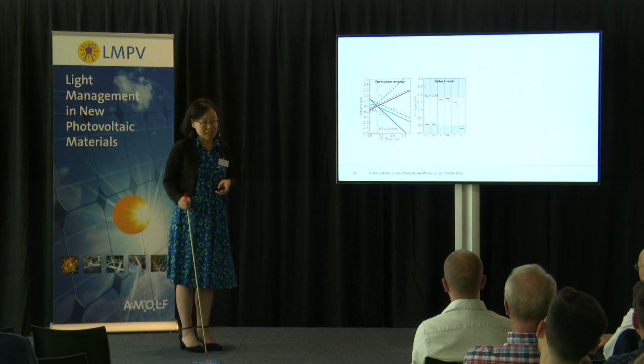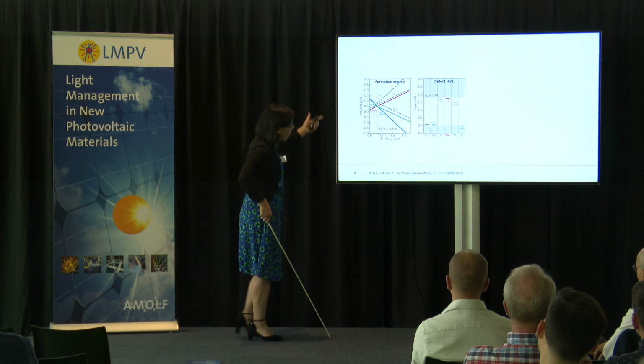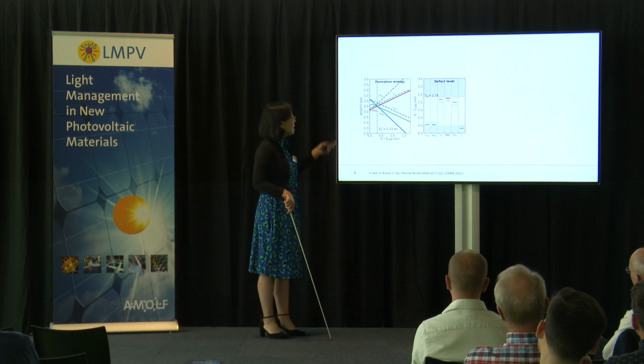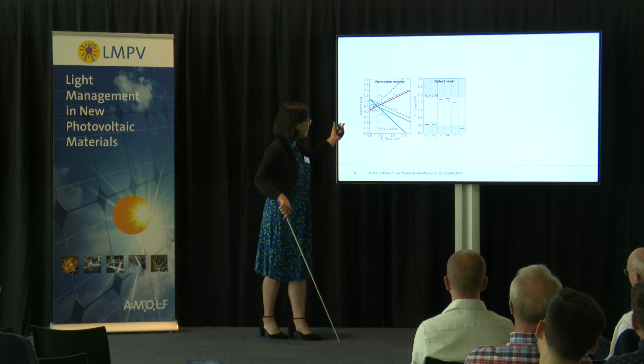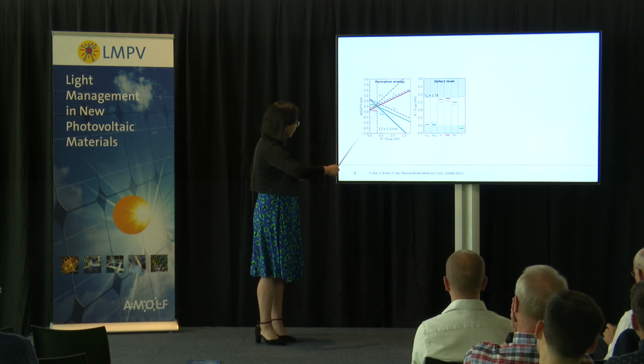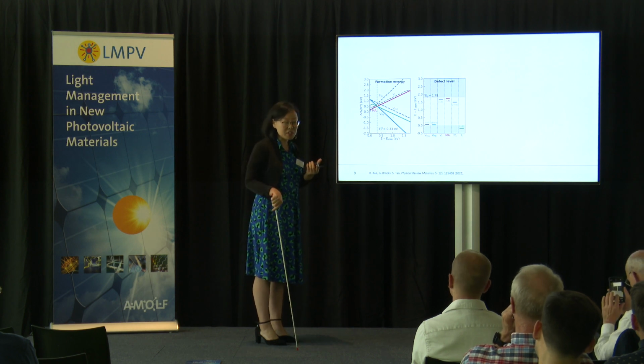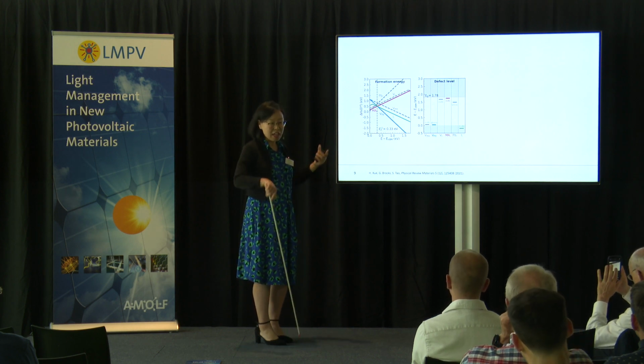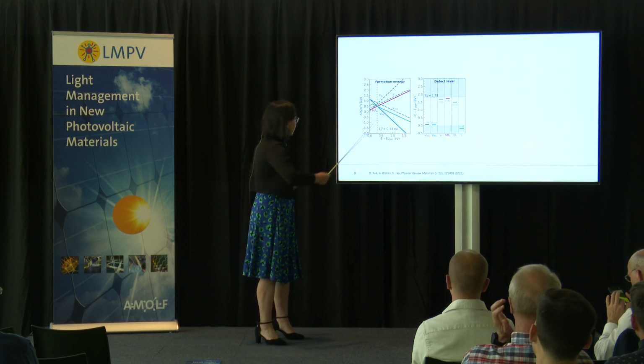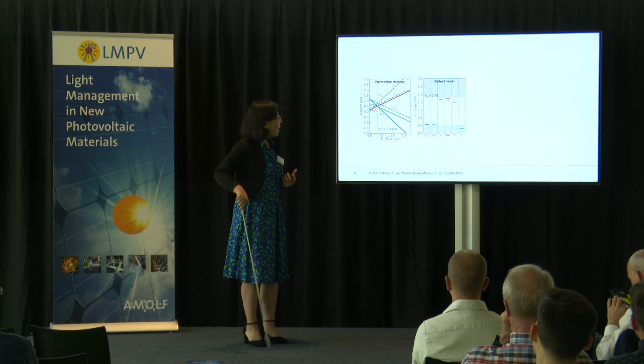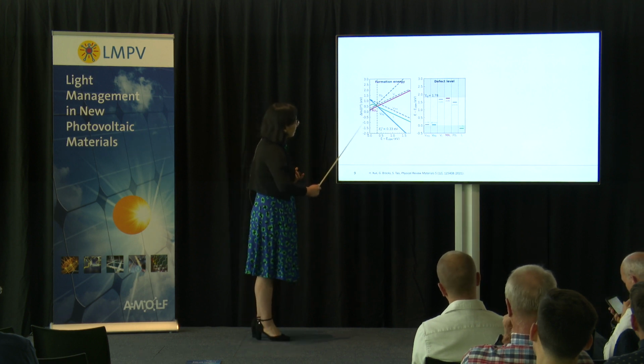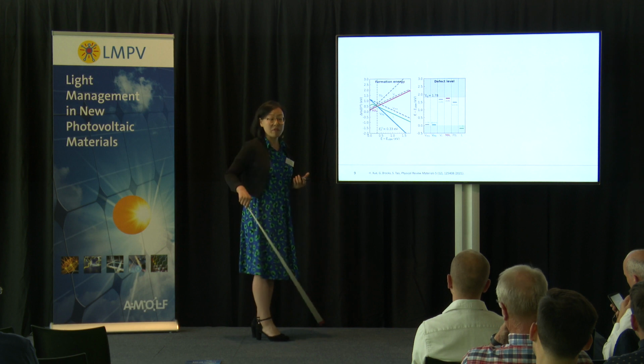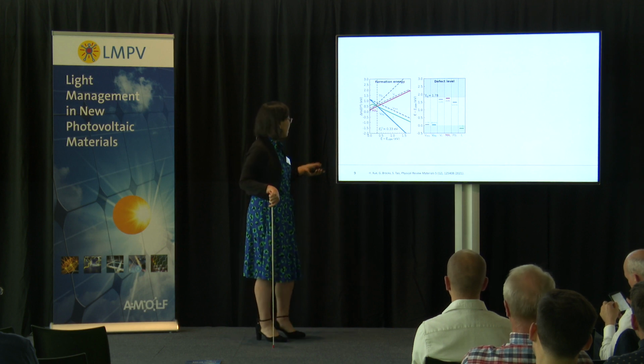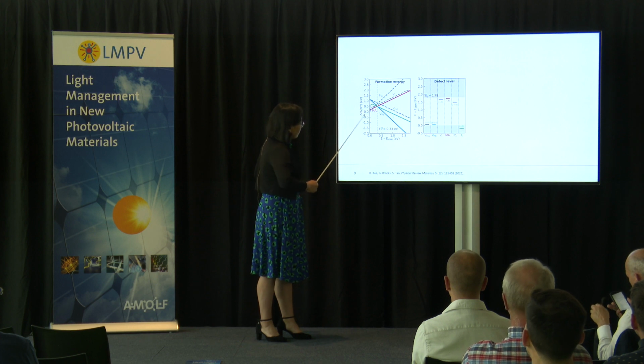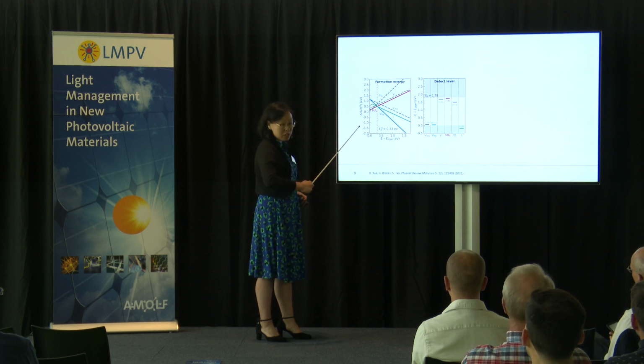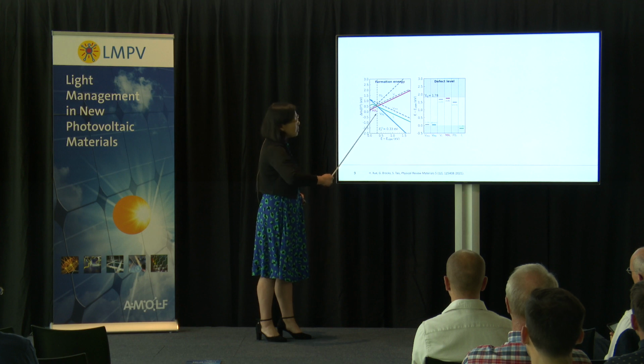Just use MAPI as an example. This diagram may be a bit more complex, but what it actually means is the formation energies as a function of the Fermi level. And you see the slopes, the positive and negative slopes, because some of the ions are positively charged, some others are negatively charged. And the charge neutral condition makes sure we actually find the intrinsic Fermi level. And the defects that are lower in this diagram have low formation energy. This means, in this case, the MA interstitial is the most abundant and is compensated by oppositely charged vacancy